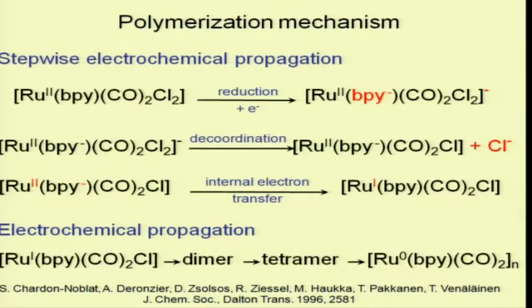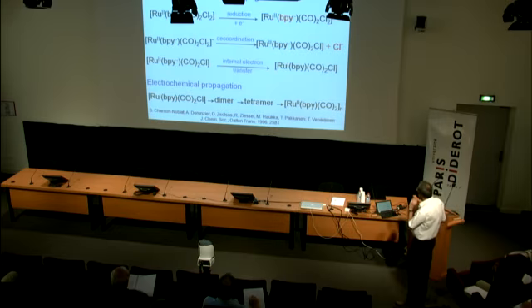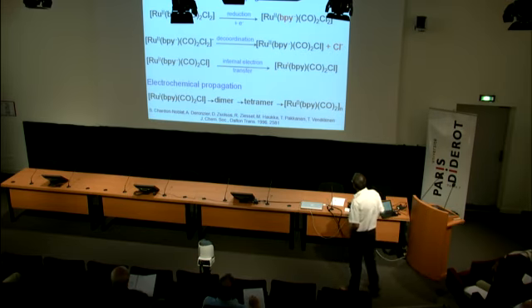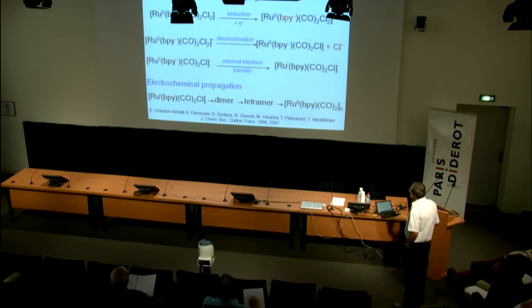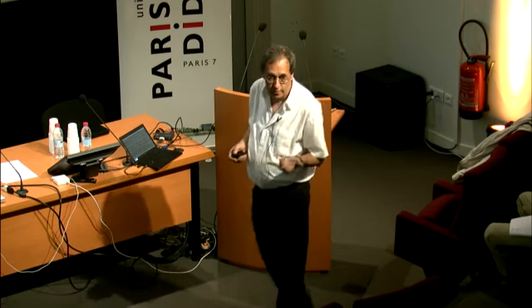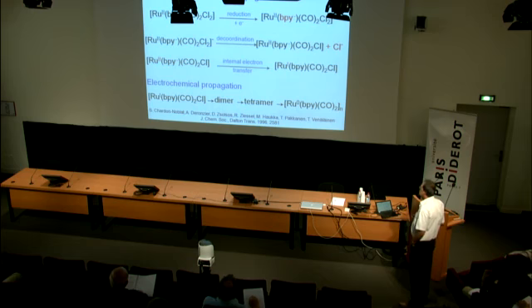Well, so how does it work? The mechanism of polymerization is just a classical stepwise electrochemical propagation. The first step involves the injection of an electron into the bipyridine ligand, followed by a fast decoordination with loss of one chloroligand. There is an internal electron transfer, making this ruthenium-1 species. At this stage, there is dimerization, and the dimer itself, we have demonstrated that by studying the chemically prepared dimers, is easier to reduce than the precursor. So that's typical of stepwise electrochemical propagation.